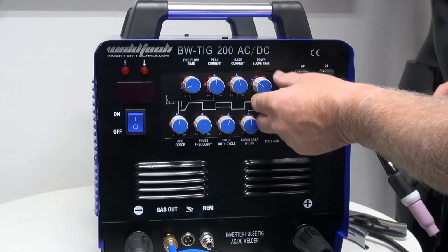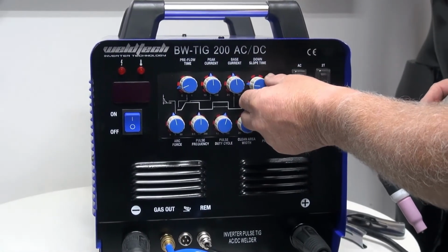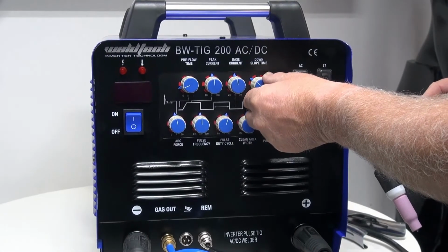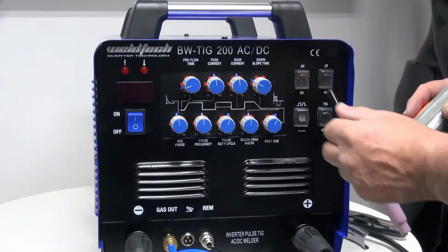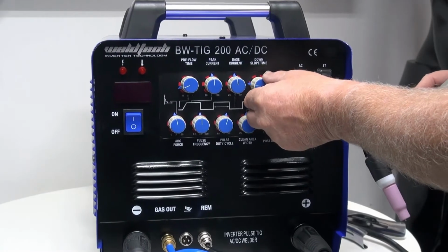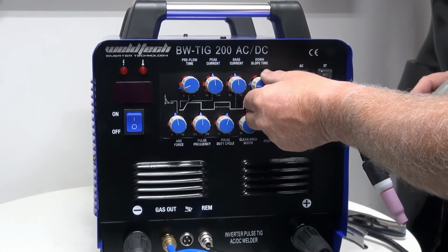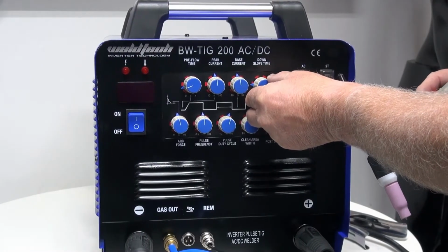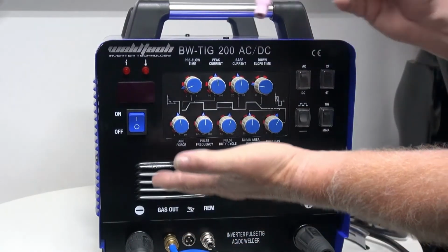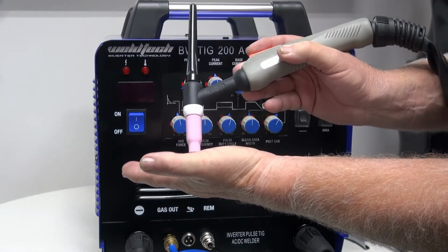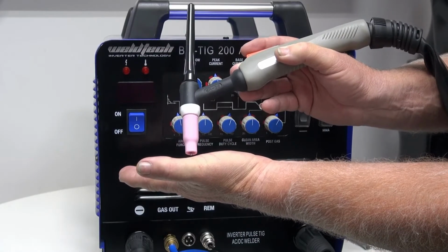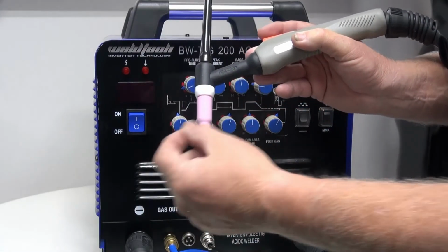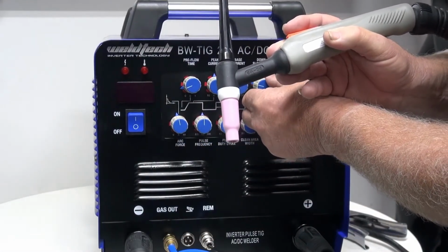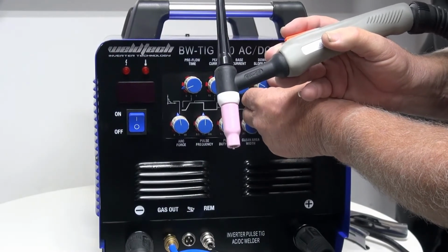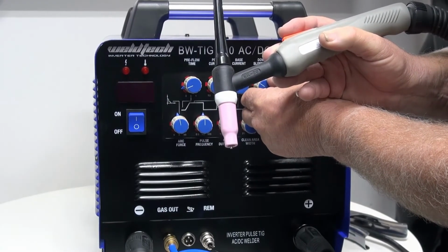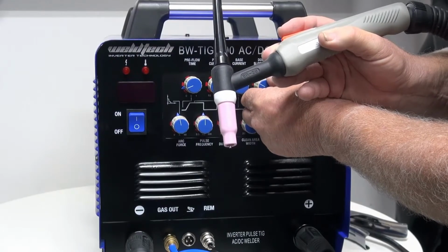The next knob that I'm going to have a look at is downslope. Downslope is used to fill up the little crater and the pinhole that can be formed at the end of TIG welding. Some people like a lot of downslope, some people like a little downslope, but you have to have enough just to let the puddle freeze over. So when I let my finger off the trigger, downslope will wind the amperage down, and this will allow the puddle to freeze so we don't get the little pinhole at the end. I personally like it set up about 1 to 1.5 seconds, which should be about there.